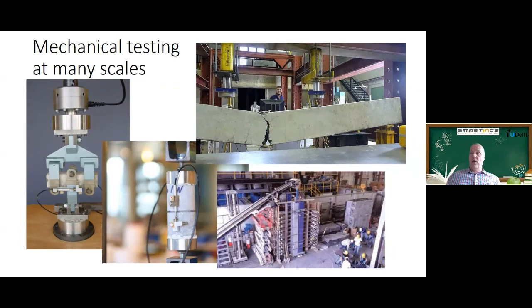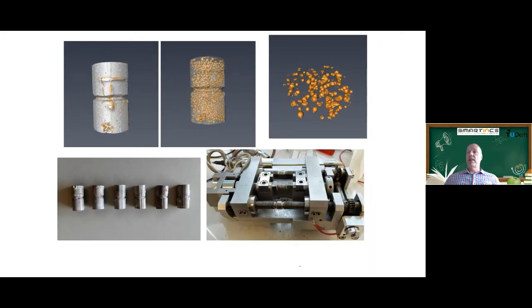These mechanical tests can be done at many scales — from mortar samples and small concrete samples up to bigger beams and full-scale specimens to create cracks and study healing. We can also do very small samples with a diameter of one centimeter, loaded in tension with capsules inside, and put them in a CT scanner to see where the capsules are and what happens. These very small samples are loaded in tension to create a crack and are studied in the CT scanner.